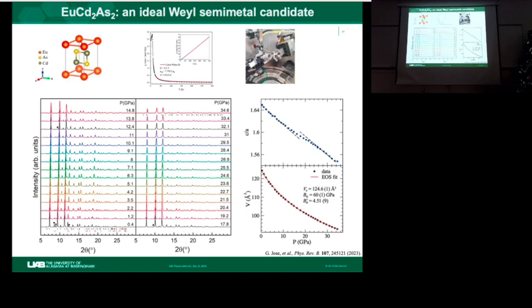So the symmetry needs to be conserved first, and then also the europium valence state needs to be maintained, because europium is a special element in the periodic table, a mid member along the lanthanides. In this case, europium is 2+, which has 7 4f electrons. However, if you are familiar with the lanthanide contraction, under pressure or temperature or magnetic field, you can easily control the valence state or the number of 4f electrons, and then you can manipulate the magnetic order or the magnetic configuration